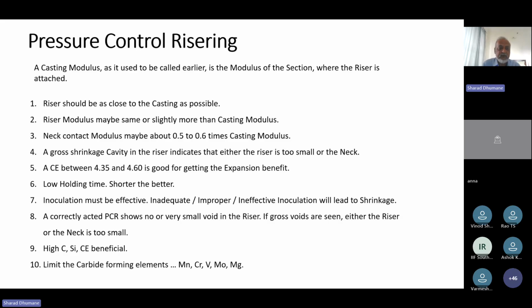Find out what's wrong with your inoculation. Most of the time, you choose very good inoculants, you do inoculation, but since the inoculation was not done correctly, your inoculation quantity becomes inadequate, and then you run into the problem of carbides. Then you start introducing mold stream inoculation, but you still continue to get the problem. I have seen this in one very good foundry where they were doing mold stream inoculation, and they had 30% cases of carbides.